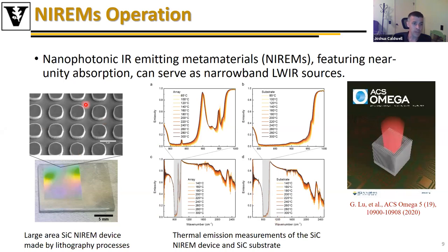And so in collaboration with the Naval Research Lab, Marco Tadger fabricated these structures here so that we could get a large area structure. This is about a centimeter on a side, with the concept of being able to get a large enough structure so we could measure the angular spread of the thermal emission. And you could see again from these structures, these give rise to relatively narrow resonances that don't spectrally shift very much as I increase the temperature. Furthermore, if I look at overlapping 2 resonant modes, I can actually get a strong enough resonance that I get an emissivity approaching that of 1. So I can get an almost perfect absorber at this frequency that also emits in both P and S polarized light. If for comparison, the flat substrate is over here, you can see within the Reststrahlen band effectively no thermal emission because it's effectively a mirror.